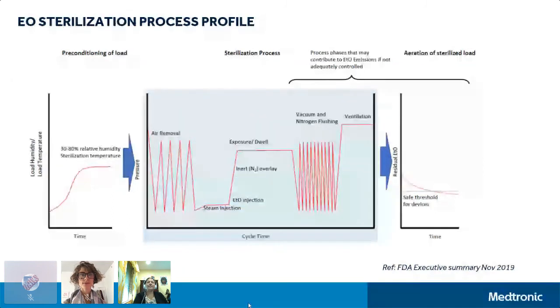And this requirement can also be traced back to one of the things pointed out by the earlier speaker on the spores, which are the most resistant bacteria to be killed. Somehow, maintaining this humidity level tries to swell up the spores and then break them. And that's why maintaining a humidity level of 30 to 80% is optimum for sterilization effectiveness. And then after the preconditioning, the sterilization process requires you to remove the oxygen to allow the EO gas to fill the chamber.